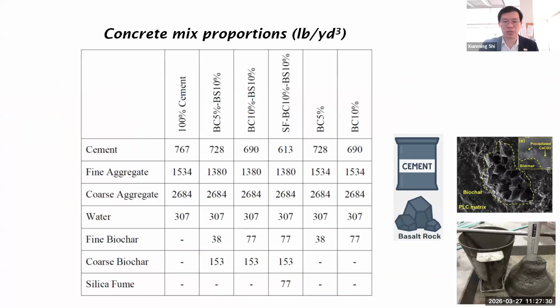So we explored several mix designs. Each column is a different mix design. Of course, for those of you who are less familiar with the pound per cubic yard, 1 pound per cubic yard is about 0.6 kilogram per cubic meter. And we used the water cement ratio 0.4 for these concrete mixtures, and the sand to cement ratio 2.0, the gravel to sand ratio 1.75.